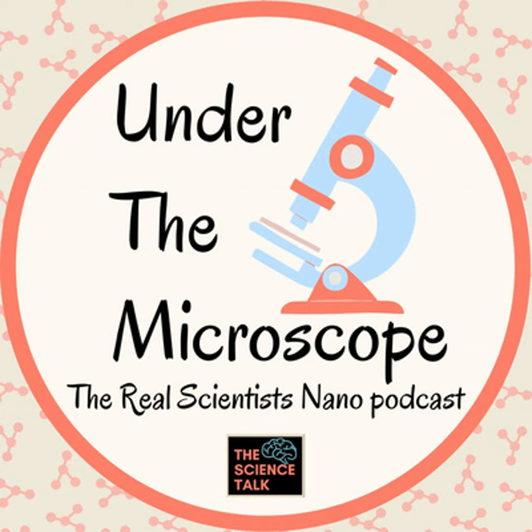And then I managed to get them to grow wires. And these wires, some of them, most of them, when it worked, they had asymmetrical cross sections. So they were no longer nice looking, usually it's hexagons, but now they had 2 different axes in the plane or perpendicular to the plane of growth. That was pretty cool. So I kind of forced the particle to stay asymmetric or not to be circular.